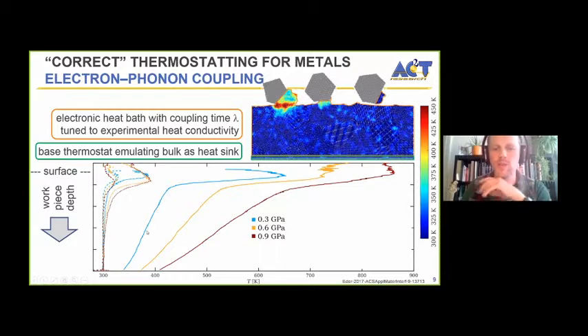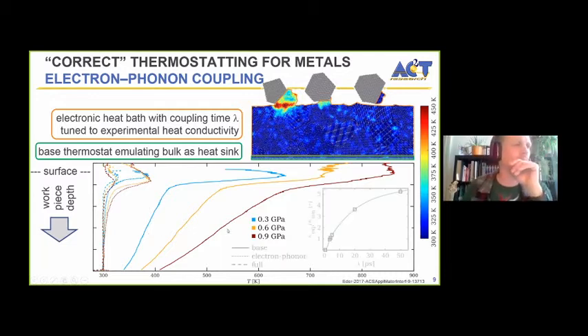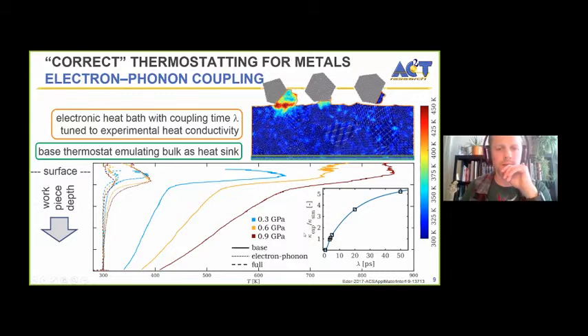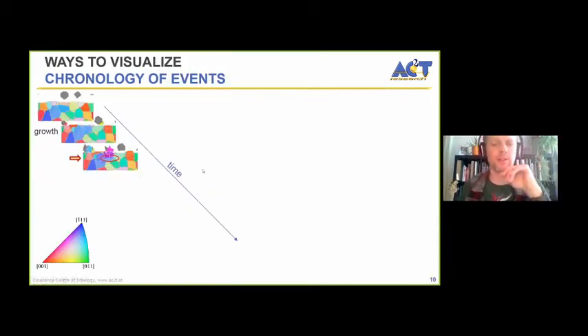As you measure these gradients, you can just plug that into Fourier's law, and you can back out a kappa, the heat conductivity in your system, and then from there on you brute force your way through, and in the end you get a fit and find that coupling time that corresponds to the metal that you're trying to simulate macroscopically. In this case, for iron, it's 3.5 picoseconds of coupling time, and I just put that into my simulation, and voila, I get the correct gradients for the heat dissipation.